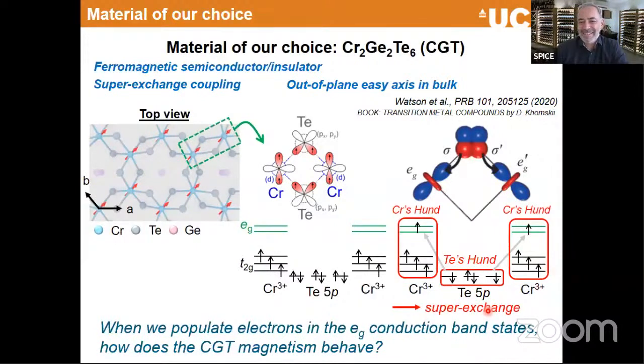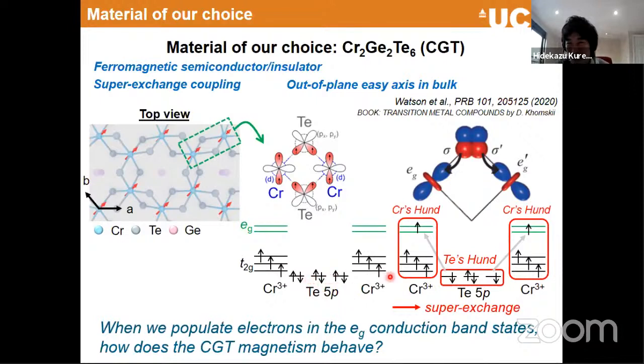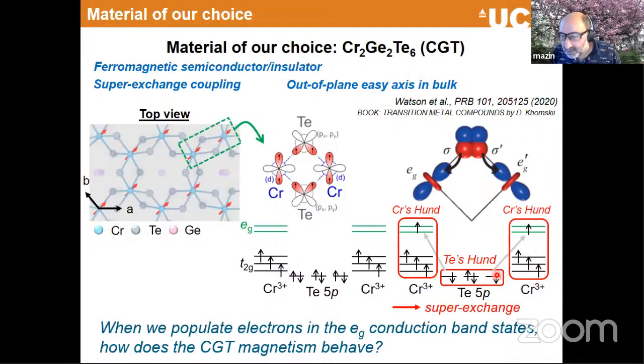That is wrong. The motivation of this case is that these two sides are like px and py, and if you make them degenerate, we cannot tell the front row very nicely. So that's the reason why we just split them. Sorry, it's much simpler. But that is actually a weak effect. This is the 90-degree Goodenough-Kanamori rule exchange. That's weak here. The main exchange is the other mechanism that you mentioned, the EG to T2G exchange, because that's proportional to pd sigma times pd pi, and the other one is pd pi squared.